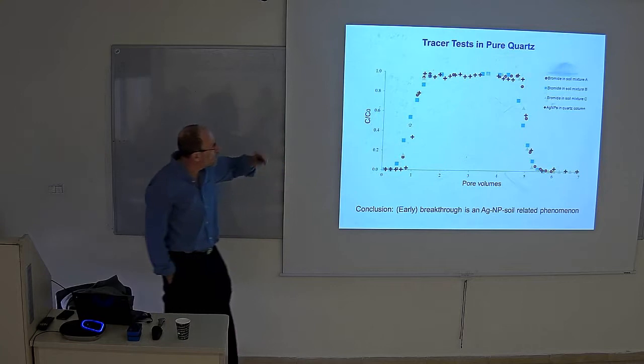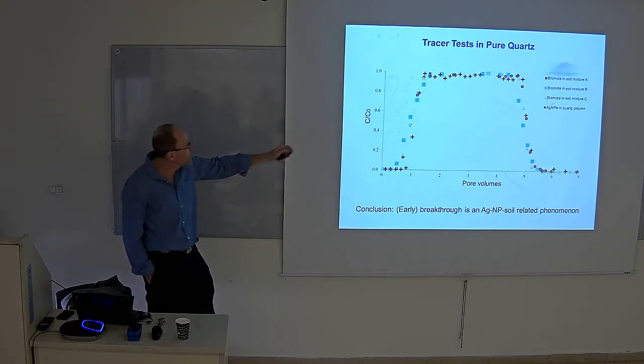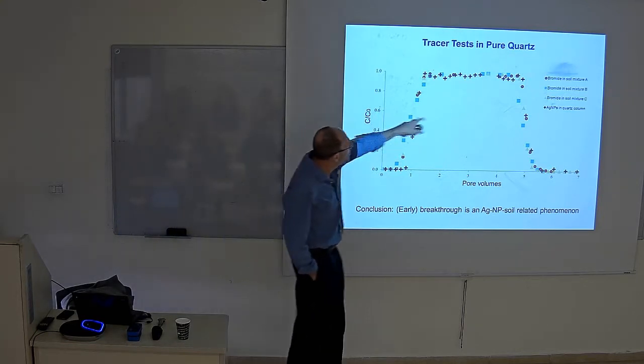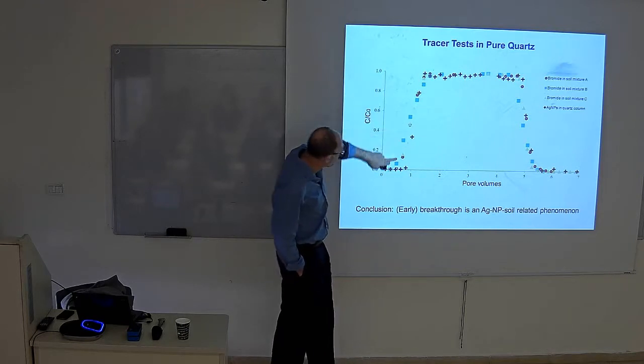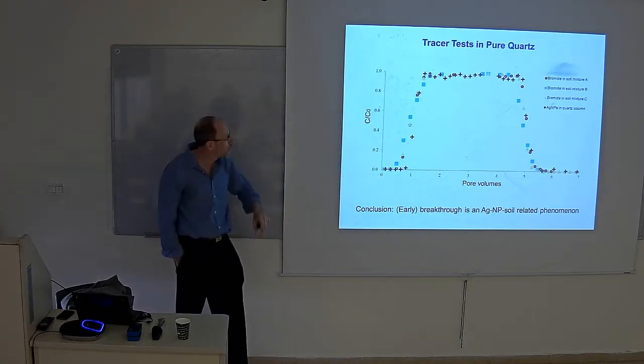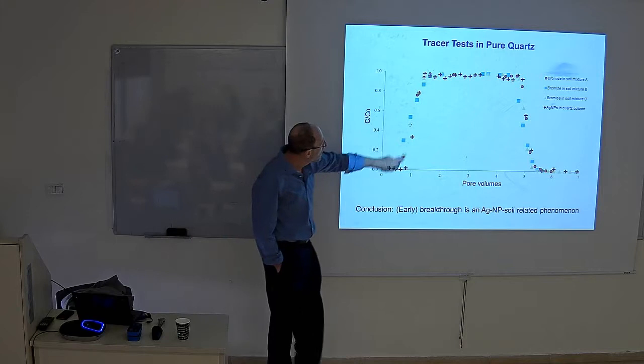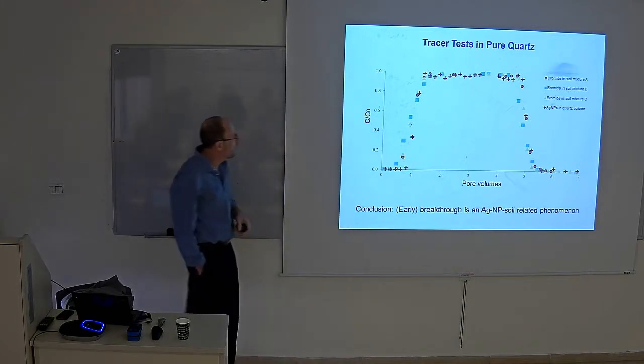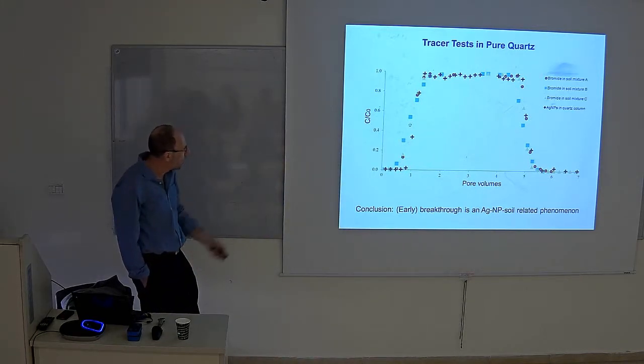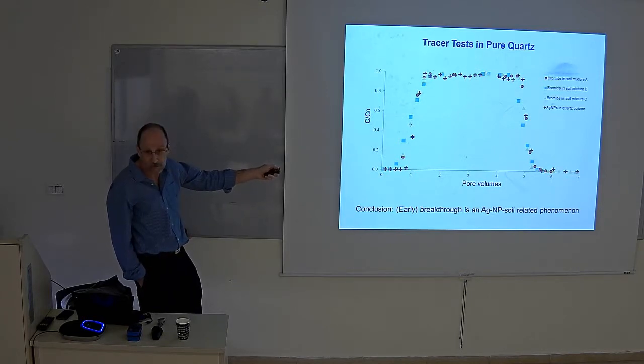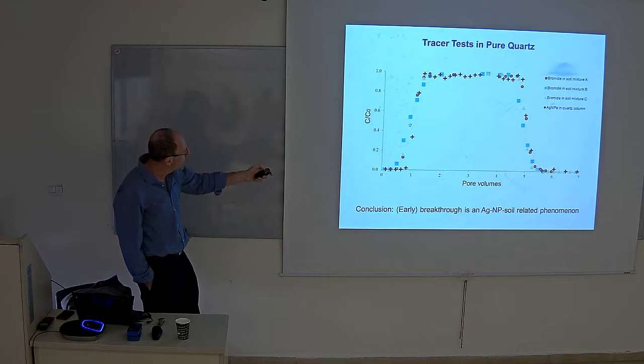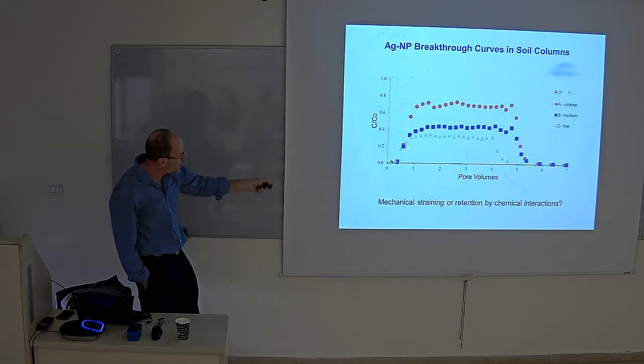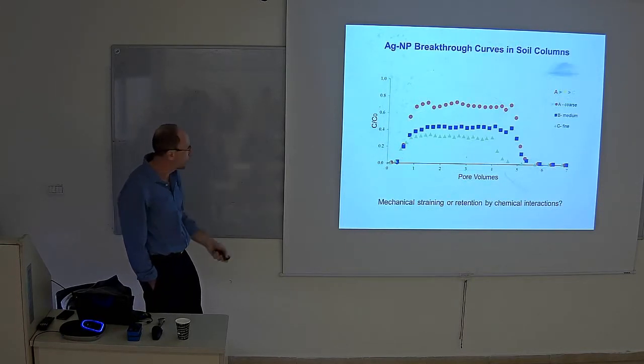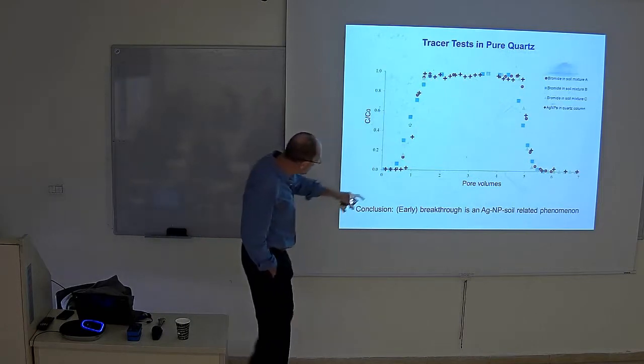Then we said, okay, let's go back, test it on quartz sand, say with pure quartz. The blue and red and green, this is all bromide, which is 3 replicates of the conservative tracer. Here you have the silver as the crosses, and you can see here we have full recovery, 100% recovery there. So in other words, the retention here, I mean, this is some chemical, physical effect for the retention. But then there's something else we noticed.